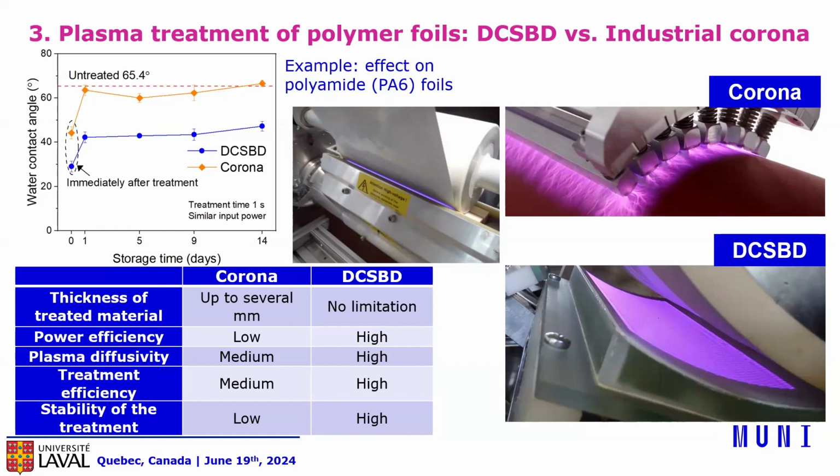And regarding the corona, we also observe such an effect, that we get very fast saturation in the treatment. So I'm quite sure that if you prolong exposure time to 3 seconds or 5 seconds in the corona, you are not able to get better results. It will be somewhere about this value. But in the case of the coplanar, we are able to go much, much lower with the contact angle.